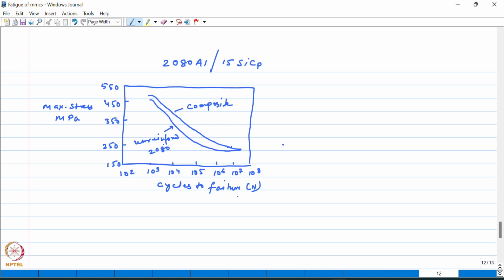Okay, so this is how the fatigue curves will look like for these two materials, the unreinforced 2080 alloy and its composite reinforced with 15% silicon carbide particles. So there are a few things that can be noted here for this condition when it is fully reversed, that is R is equal to -1. So the first thing that you can note here is the fact that the composite is having a better fatigue life compared to the unreinforced alloy, as you could see from here.